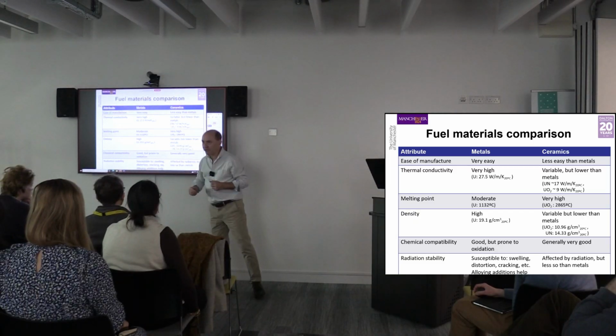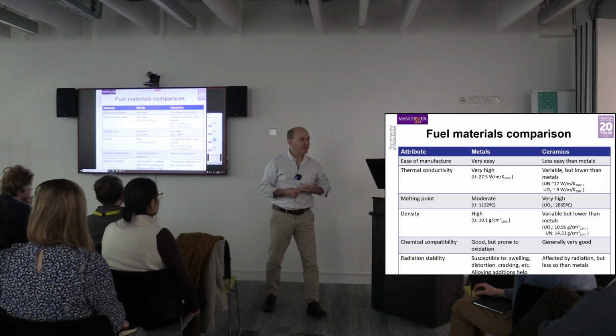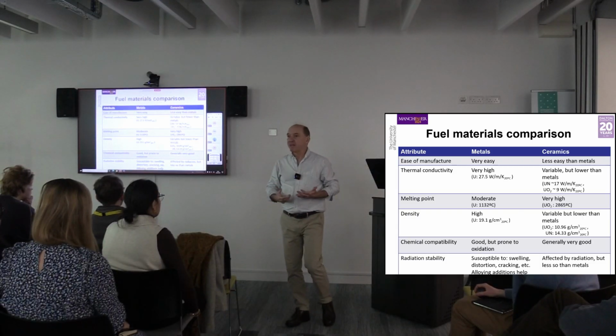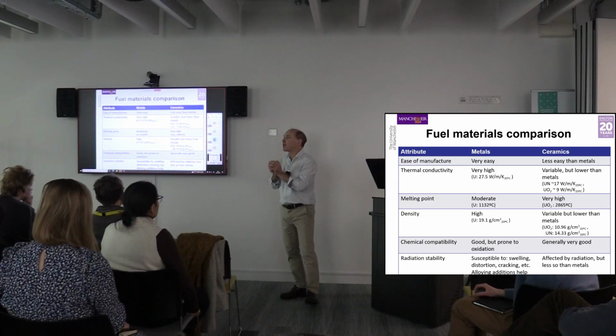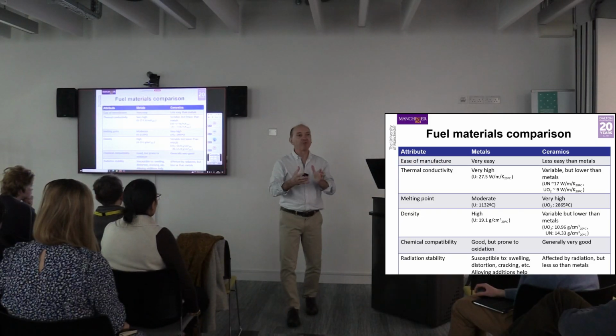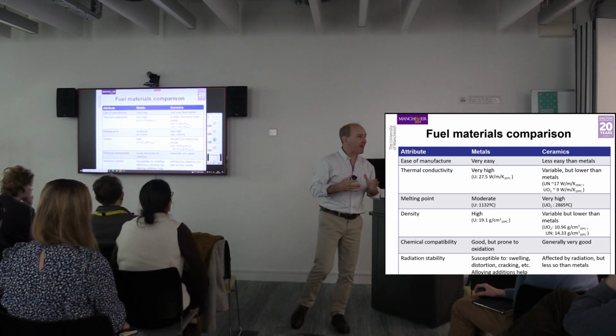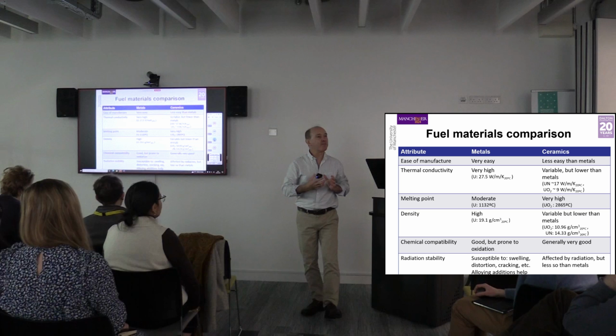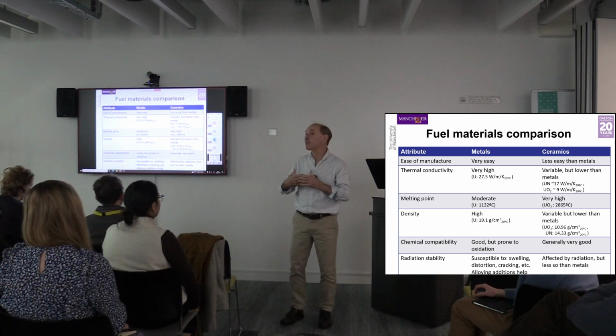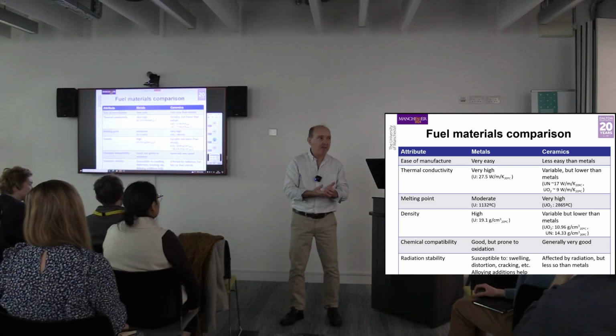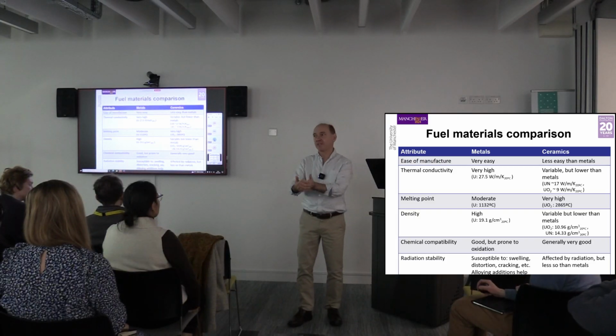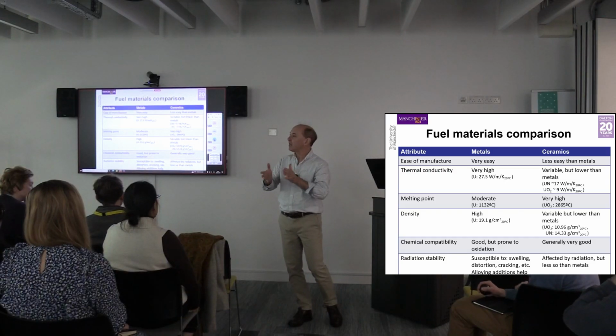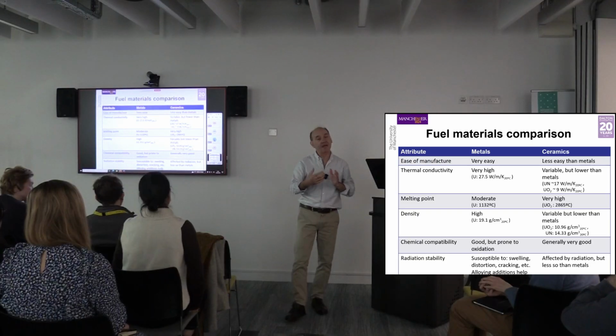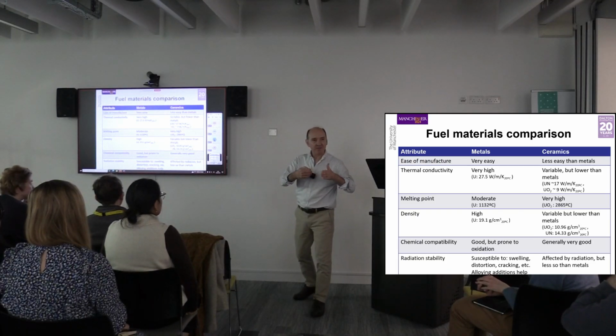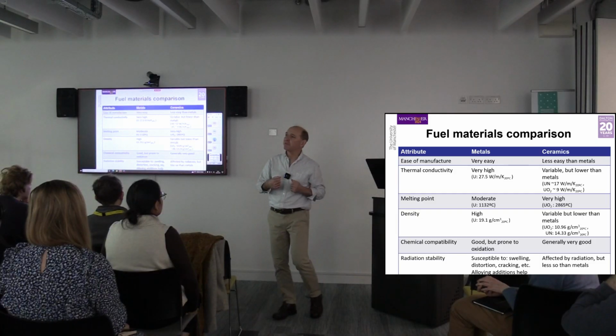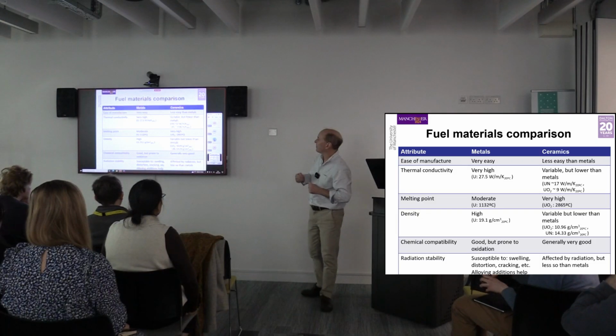Density, why on earth should we be concerned with fuel density? Why should that matter? Simply because density is an indication of how much material you've got in a certain volume. If your reactor volume is fixed, and it is, you're not going to suddenly make your reactor much bigger overnight, then the density of the material you can put in it tells you how much fissile material you're putting into the core of a reactor. If you can double the density, you've put twice as much fissile material into the same reactor as you could otherwise, which means that either you can get more power out of the reactor or you can operate it for longer before you have to shut down and do a refueling. So actually density really matters, surprisingly.